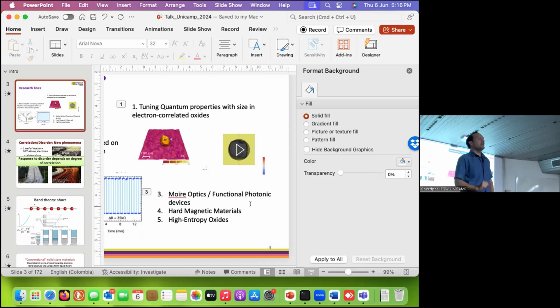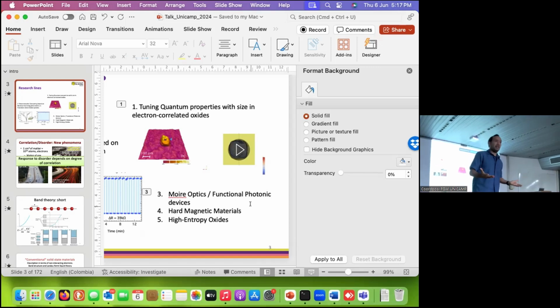But that wasn't the idea. The idea was that once you have the particle, I forgot to say that we put a contact on top of the silicon nitride and at the bottom. So the whole machine was doing transmission. But we put some contacts. We calculate how much we will have in order to have enough X-rays going through. And then we apply voltage. And what I want to see is the deformation of that particle by voltage.